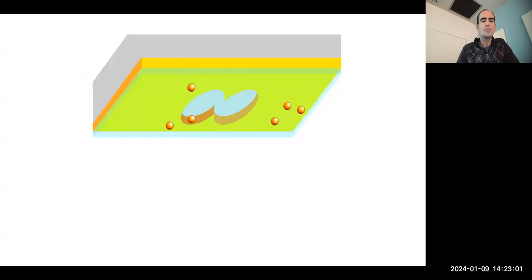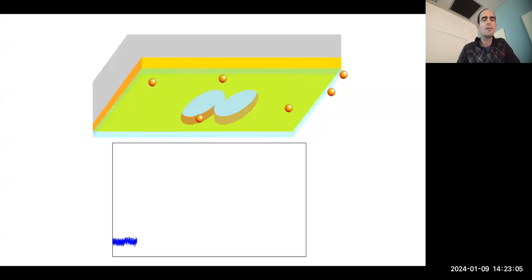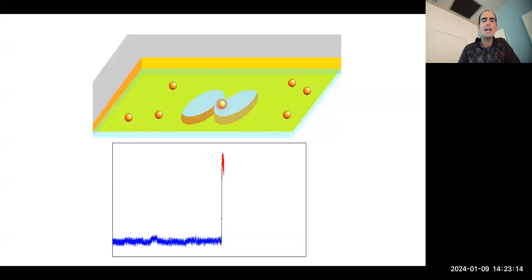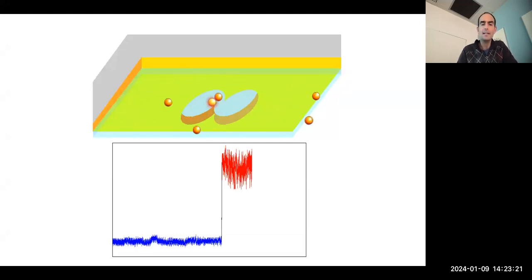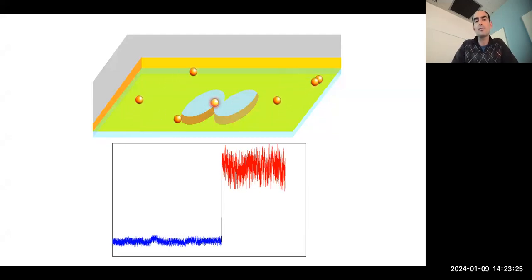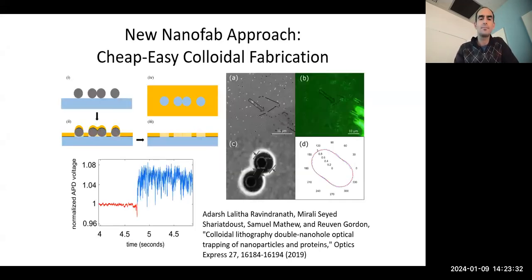So what do you see in your experiment? I showed you that we see the particles typically floating around in solution. We shine a laser beam, and if we look at the transmission through the aperture shown in blue, when a particle gets trapped, all of a sudden you see a large jump. Then the particle moving around in the trap tells us about the size of the particle, giving fluctuations in the intensity of the laser. This tells you about the hydrodynamic size, how it's moving in the liquid, so it gives a lot of information about the particle itself.